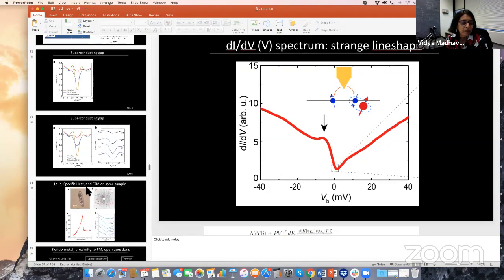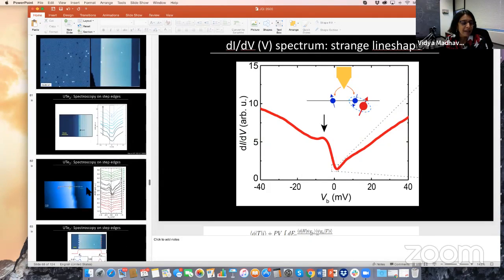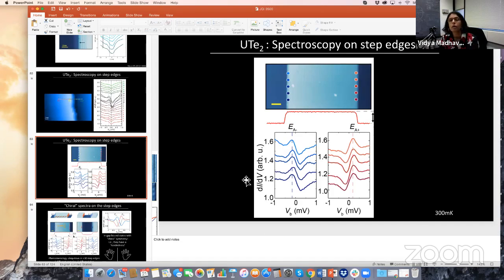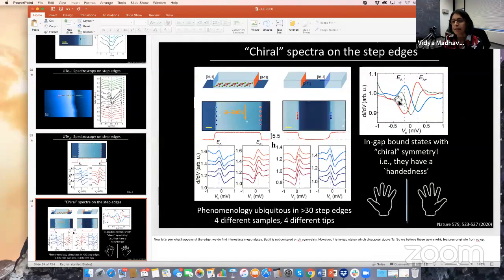So the interesting thing that we found, and I'll just show you one slide and then I'll stop, is this. What we found is that if you go to the step edges of this material, you find this strange line shape. The superconducting gap in the system is this dotted line. It's 250 microvolts. On the step edges, you see this funny feature with a peak that lies inside the superconducting gap.